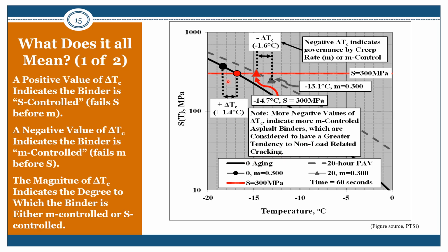Again, this was unaged and then aged 20 hours in the PAV, and here we have a positive 1.4 degrees C, and on that 20-hour age we have a negative 1.6 degrees C. The negative delta TC indicates that it is governed by the creep rate or M value, while the positive delta TC indicates that it's governed by the S value or the stiffness of the binder.